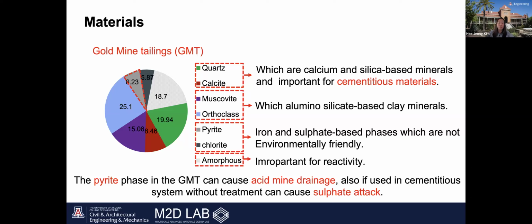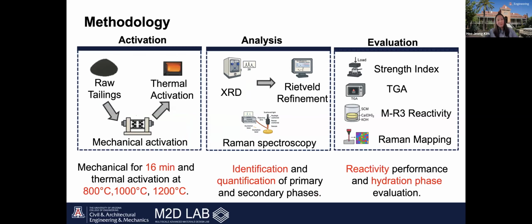And after the characterization, about 18.7% of the material is amorphous, which is a reactive portion that can contribute to the cement hydration. So we were able to confirm that amorphous phases are 18.7% in our gold mine tailing samples. And for activation, we used mechanical and thermal methods to increase the energy and break the crystalline bonds, making the tailings more reactive.